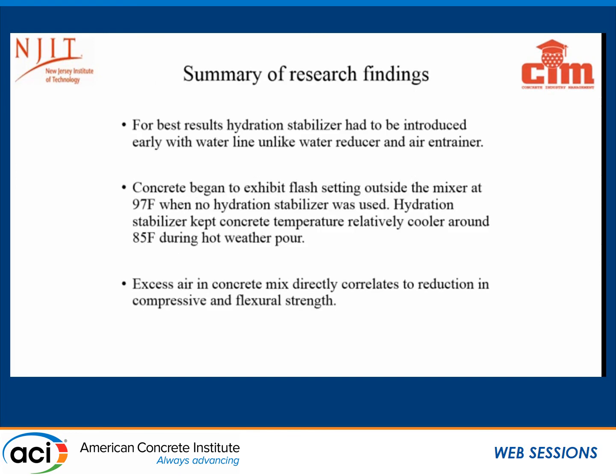Now, the mixes without hydration stabilizers started setting up pretty early, and the ones with the hydration stabilizer gave us the extended times, and this last one pretty much extended here. We had to redose with air entrainment on a couple occasions.